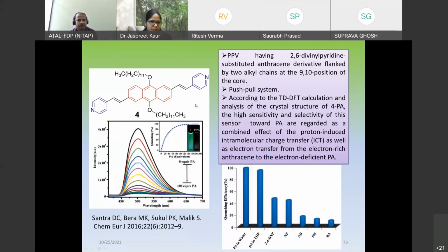So there are alkyl chains at the 9 and 10 positions of the anthracene core, and as per the DFT calculation of the crystal structure of this compound, they show high sensitivity toward picric acid because of the combined effect of the PET and the ICT phenomena. So this is picric acid in water, picric acid in THF. Aggregation is also there in water. Picric acid is detected in the aqueous medium, so aggregation is also there.